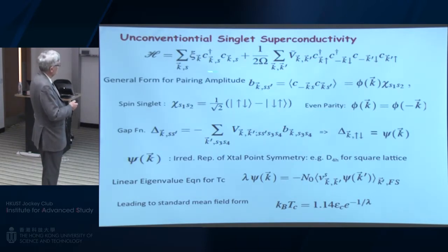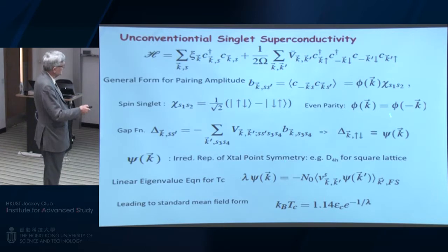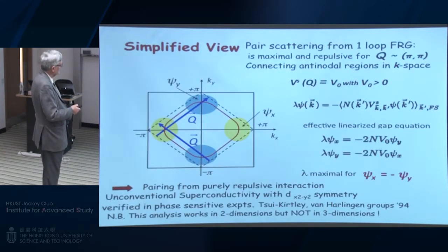So if we want to do unconventional superconductivity now with repulsive interactions, then as I said before, this gap equation, the linearized gap equation which determines Tc, has a problem, because if we were to take psi here and psi here with the same sign, and we have here a repulsive positive interaction, then this minus sign means we can't get a solution of this linear eigenvalue problem for Tc. So we have to, as I said before, make a sign change in this amplitude, no longer a constant around the surface, but look for some irreducible representation of the crystal point symmetry, which has sign change as a function of angle.